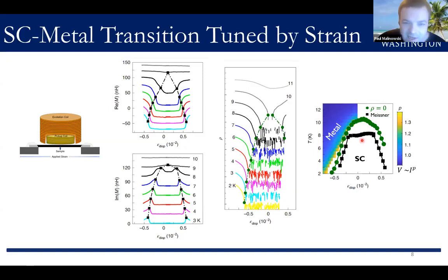Yeah, that's a great question. I'm not sure. I know that previous work has shown that the critical currents or the pinning of the vortices actually depends a lot on the domains. So when you detwin the crystal, you can get changes in the critical currents, for instance. And I think that might also help explain this, because you see that the thermodynamic measurement is quite flat, whereas the TC measured by resistivity is changing a little bit here.